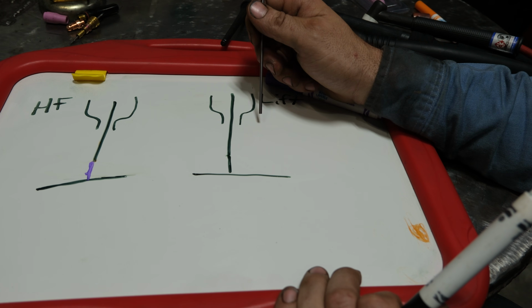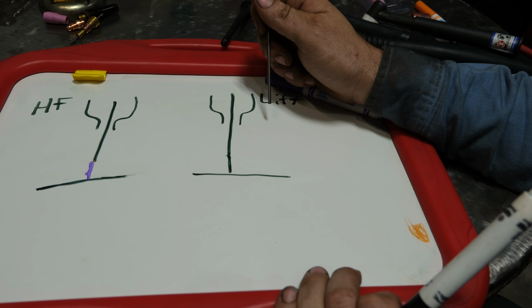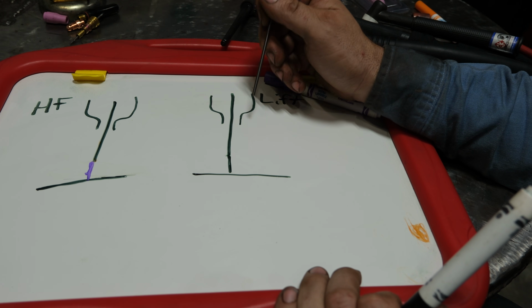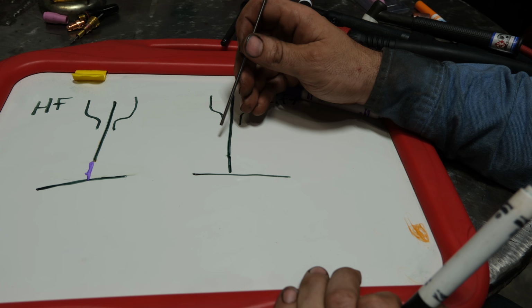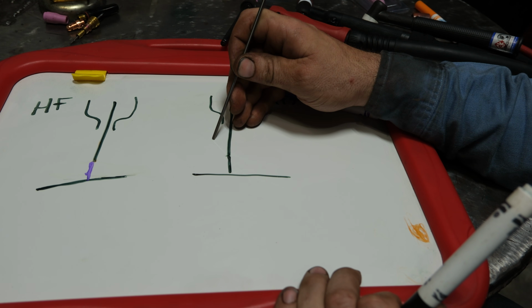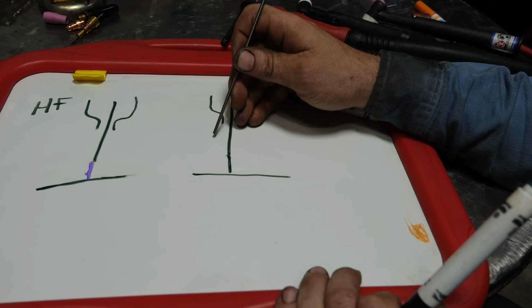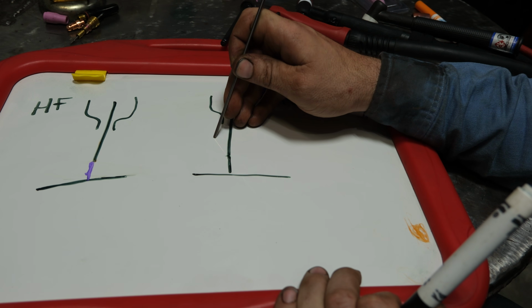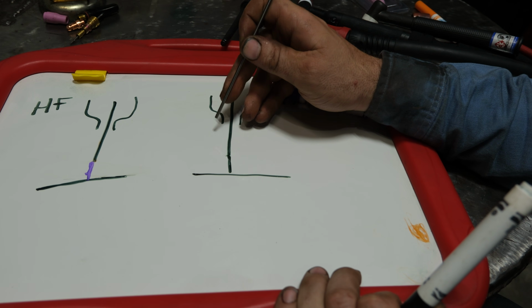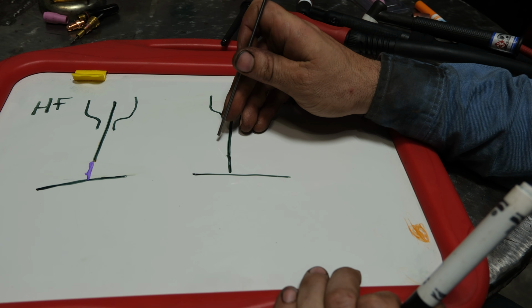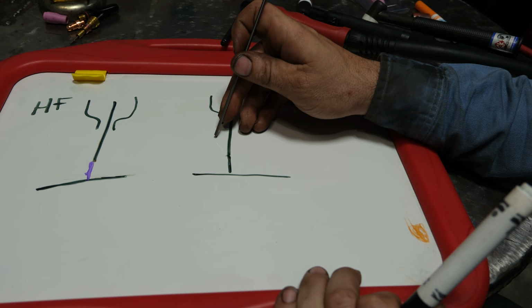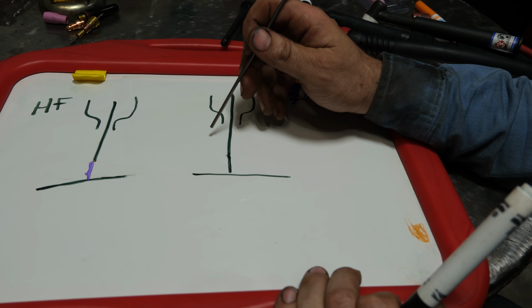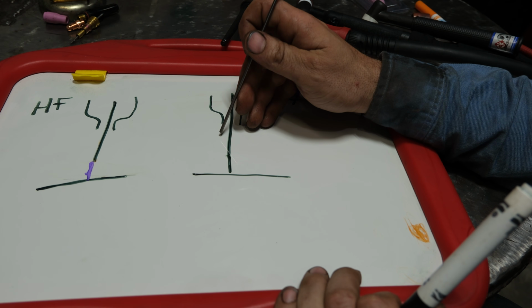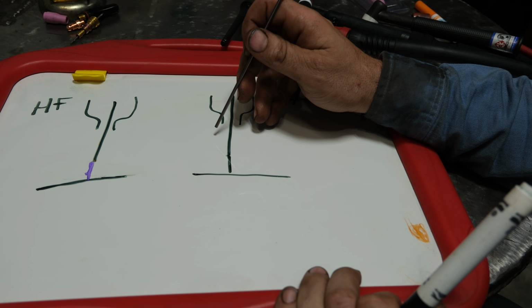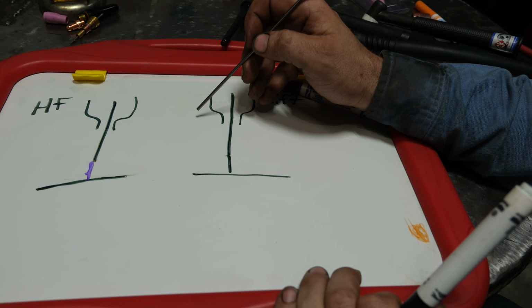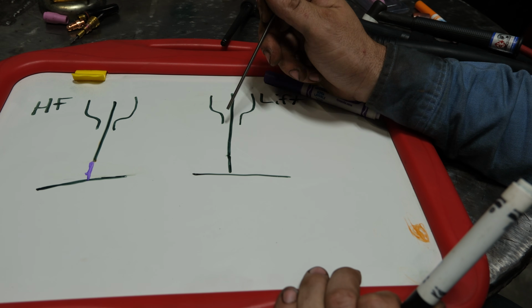For general fabrication, it's far less preferred for me and for most people. The downside really primarily comes from when you touch the tungsten and you lift it, the possibility of getting the tungsten stuck to the material, depending on how good its lift starting mechanism is, is pretty high. And if that happens, you've now contaminated your base material with tungsten, and that can be a point where a crack will form, so it's undesirable. It's much easier to get clean starts, obviously, with high frequency.